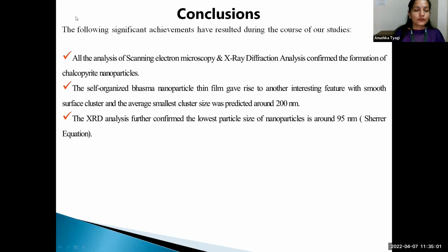The conclusions of this study are the following. Significant achievements have resulted during the course of our studies. All the analysis of scanning electron microscopy and X-ray diffraction confirm the formation of chalcopyrite nanoparticles. The self-organized Bhasma nanoparticles thin film gave rise to another interesting feature with smooth surface clusters, and the average smallest cluster size was predicted around 200 nanometer. The X-ray diffraction analysis further confirmed the lowest particle size of nanoparticles is around 95 nanometer.